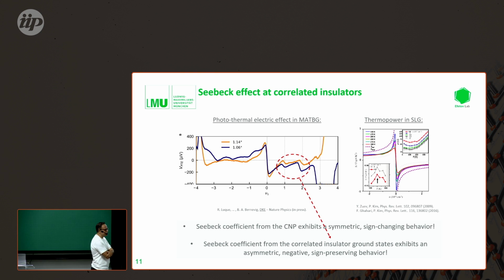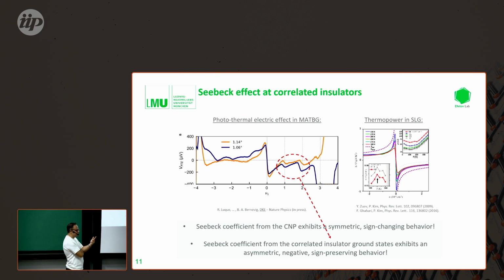Oh, pretty. So there are two ways. It's from the band edge. So the electron filling of the flat bands, right? So we know exactly when the flat bands end, there is a gap. So from this position of the gap, we can know this. And there's a second way we can measure Shubnikov-de Haas oscillations, which then culminate exactly at the band edge.